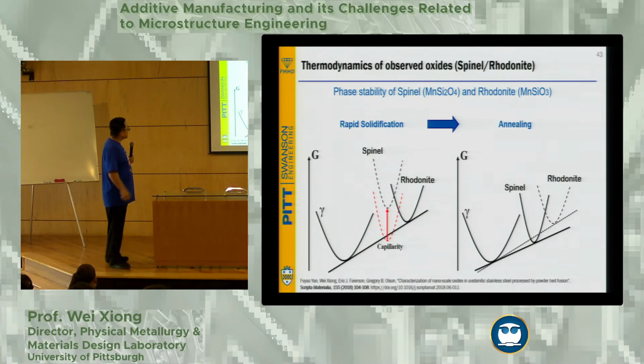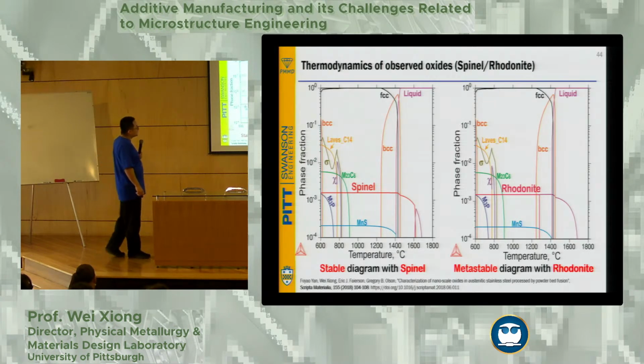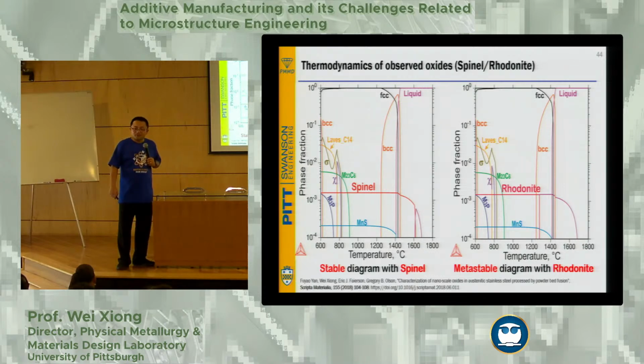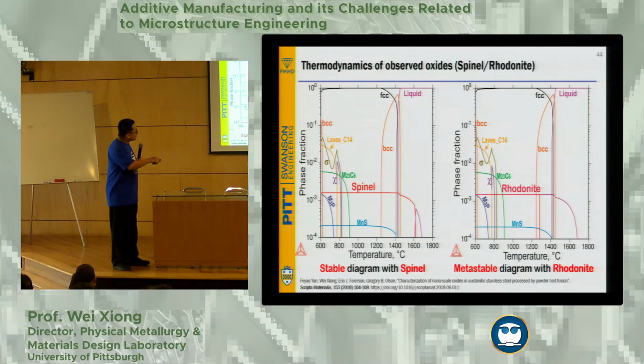After you do the annealing, the spinel starts to show up, so then you can see the gamma phase together with the spinel. So how do we confirm it from the Thermo-Calc calculations? You can easily do one calculation in less than 5 minutes. What do you do? Suspend spinel. Because the Thermo-Calc database already has the rhodonite system, therefore the rhodonite shows up in exactly the same amount as spinel.